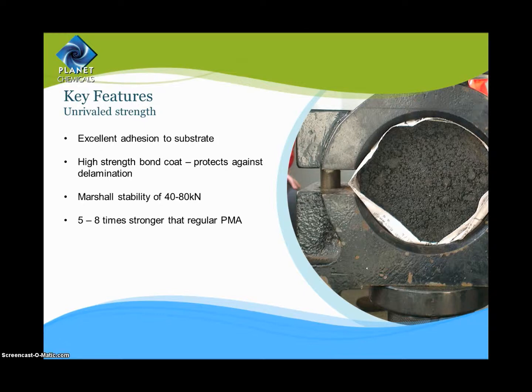Epoxy asphalt forms an excellent adhesion to the substrate and resists delamination even at higher temperatures. Featuring a Marshall stability of 40 to 80 kilonewtons, epoxy asphalt is comparatively 5 to 8 times stronger than regular asphalt.